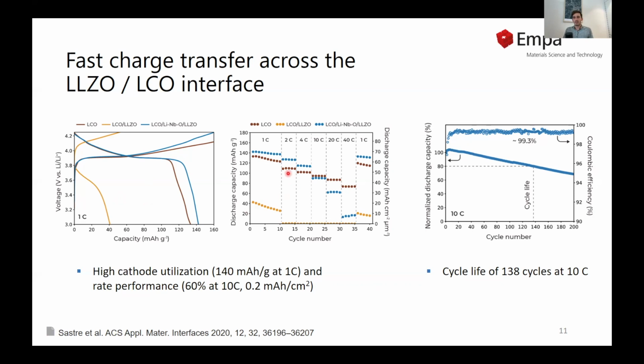We also investigated the rate performance of such a half cell. The modified half cell, the interface modified half cell, shows comparable rate performance to the bare LCO up to 10C, but then at 20C and 40C, the capacity drops probably because of this added resistance. On the other hand, the non-modified half cell shows barely any capacity at higher rates than 1C. We also assessed the long-term cycle life of such a half cell, and we were able to achieve a cycle life of around 138 cycles at 10C.